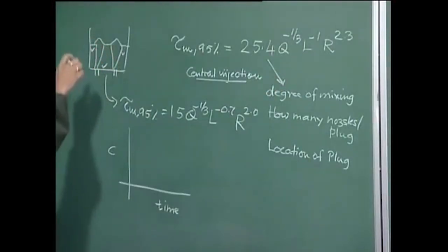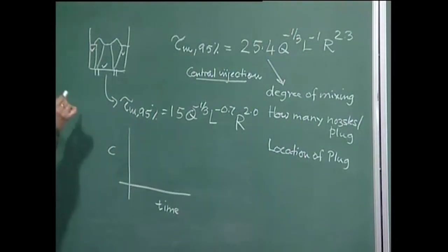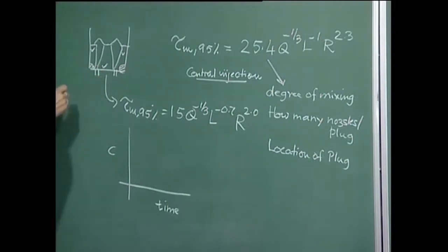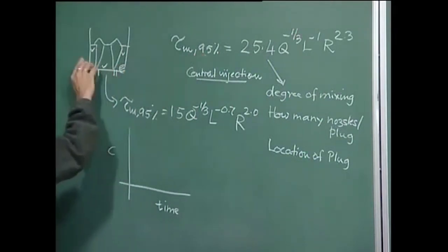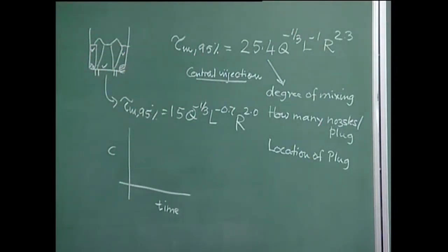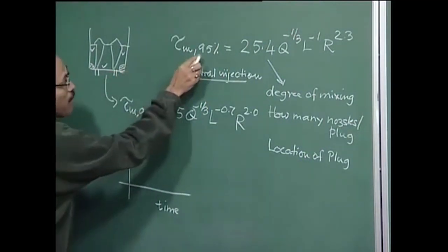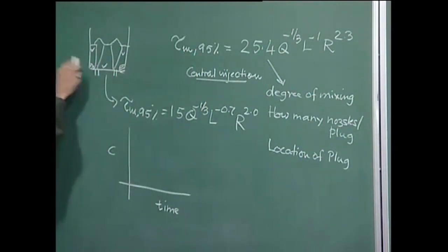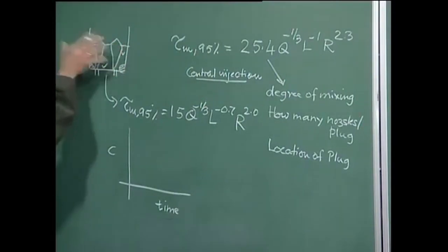What we are interested in from an engineering sense is a bulk or reactor mixing time, and that is typically characterized by the mixing of the slowest moving region. By the time the slowest mixing region is mixed up to 95%, we can say the rest of the system is going to be perfectly homogeneous. So we have to identify which is the slowest mixing region and ascribe the mixing time accordingly — that mixing time represents the bulk or reactor mixing time.